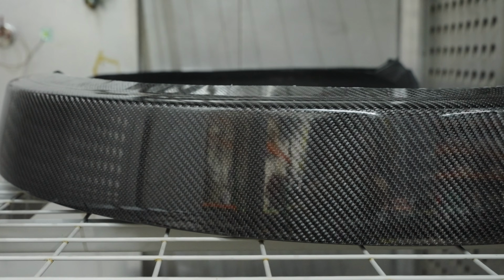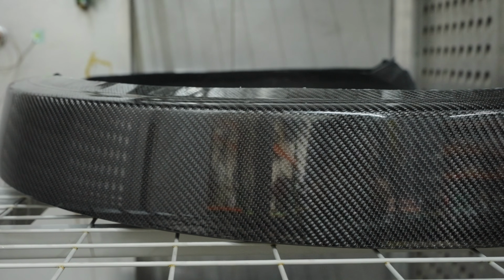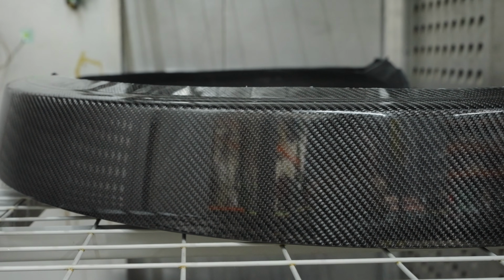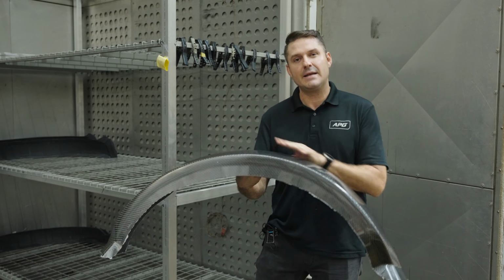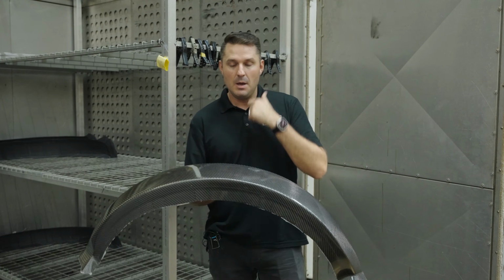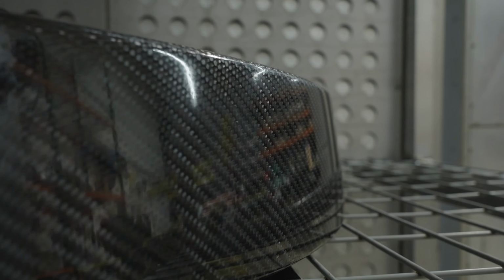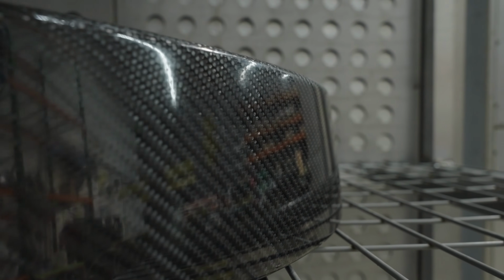So the parts will sit up with a slight increase, about 140 Fahrenheit, just to reach some temperature stability so we can do a freestanding post-cure to free up the molds. But look at that surface quality. I would consider this a perfect part, but we're not done yet. This part needs to be post-cured.